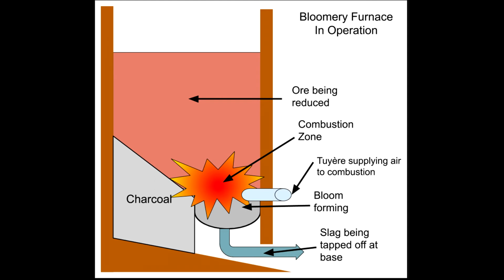This process actually begins to happen at only 300 degrees Celsius or so. But wait, that hematite we're reducing didn't come to us pure. It came to us embedded in other kinds of rocks called gangue. And this is why we need all of that heat. Most of these impurities from the ore are going to be silica, silicon dioxide, and alumina, aluminum oxide. We need those gone too. In modern furnaces, a flux, typically limestone, is introduced into the mixture because it will readily bind to these compounds to get them out of the iron.